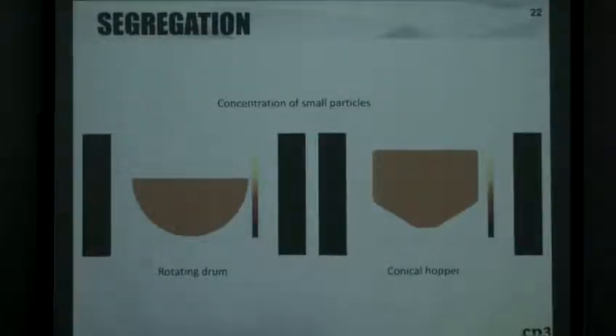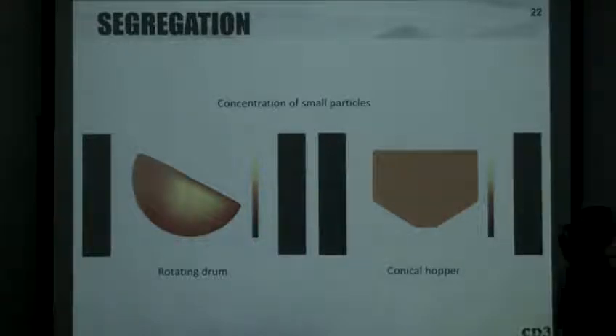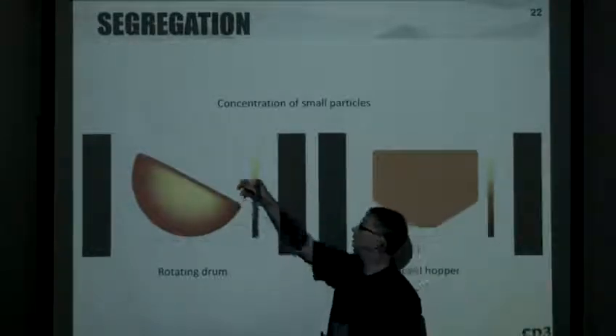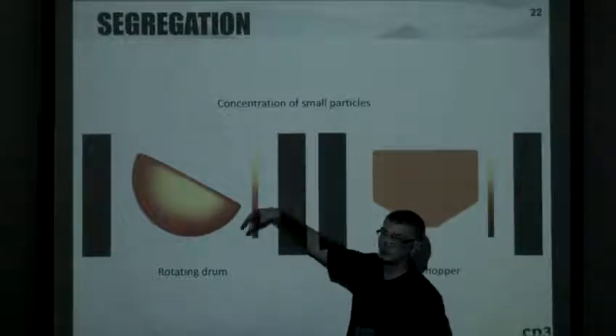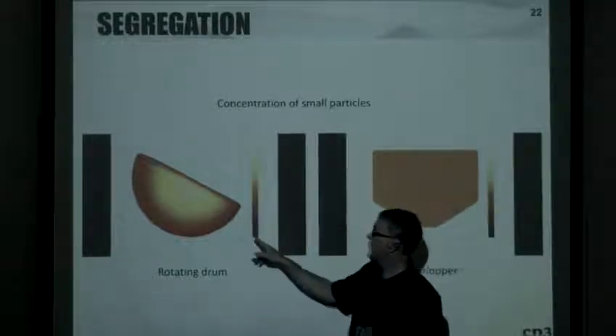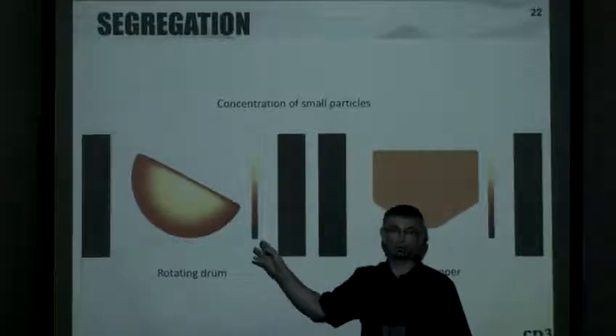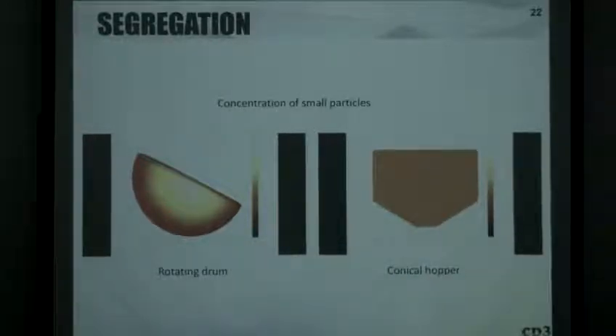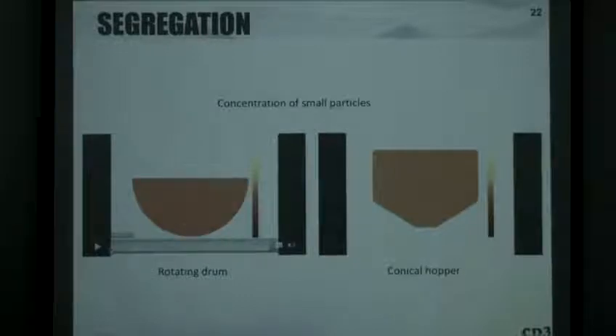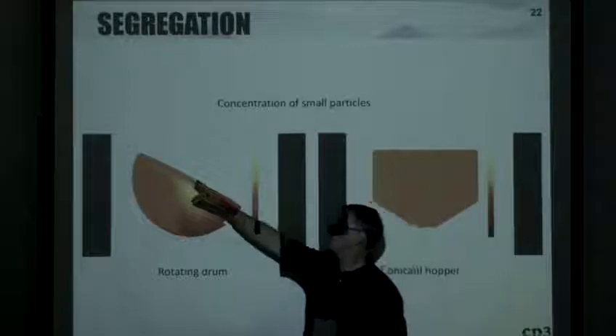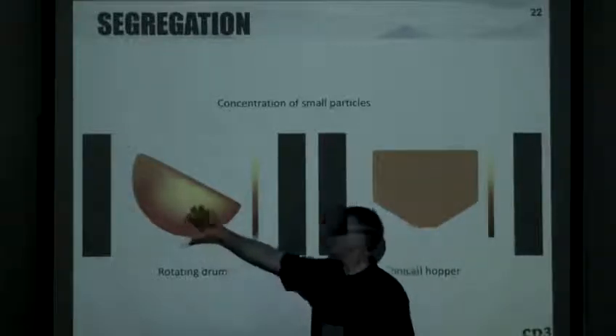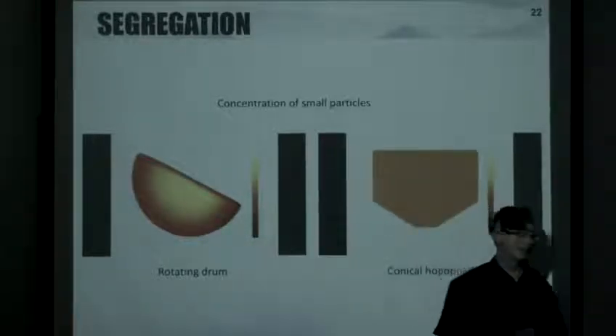So the last thing I'll talk about is segregation. The previous work was dealing with just blending, but now we're dealing with segregation, so two different particle species. What you're seeing in this rotating drum simulation is the concentration of small particles. Yellow means a lot of small particles. Dark colors mean mostly big particles. This is a classic thing where, as you rotate a drum, the small particles avalanche down the surface and then collect toward the center. And you get a stationary behavior after some time.